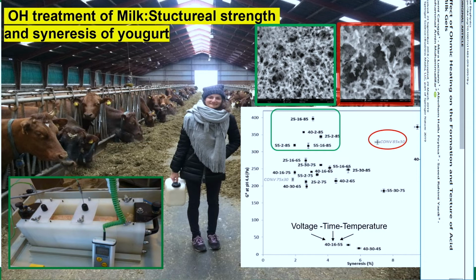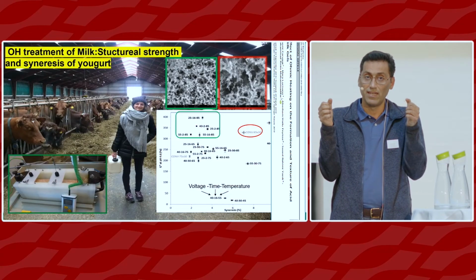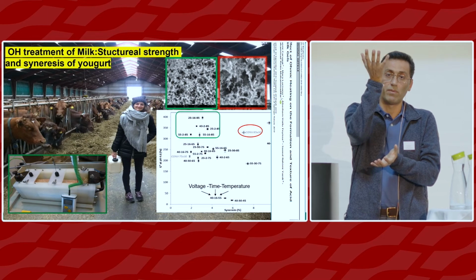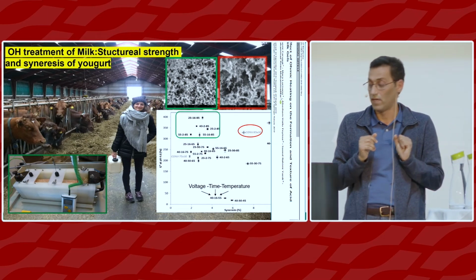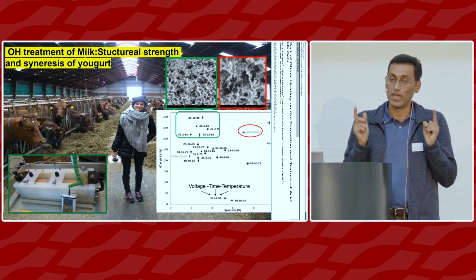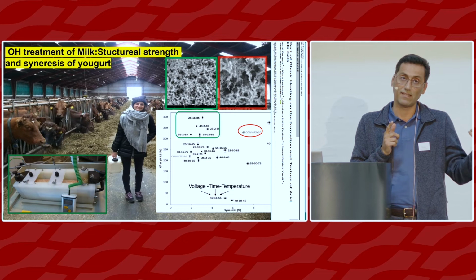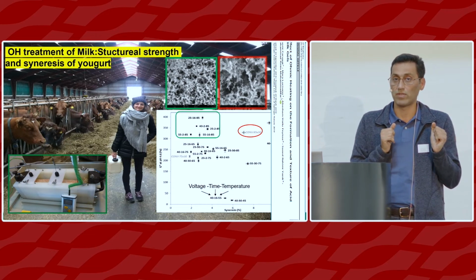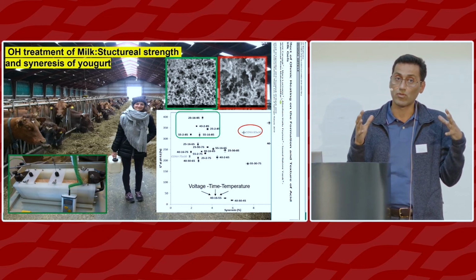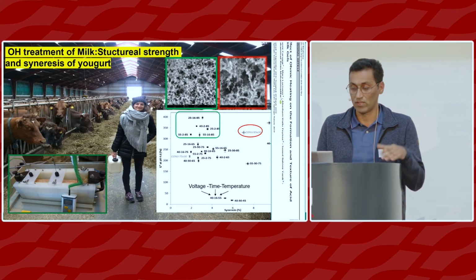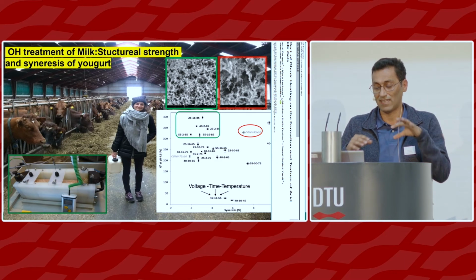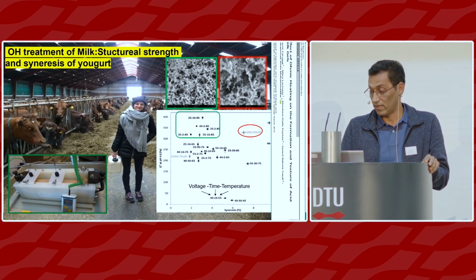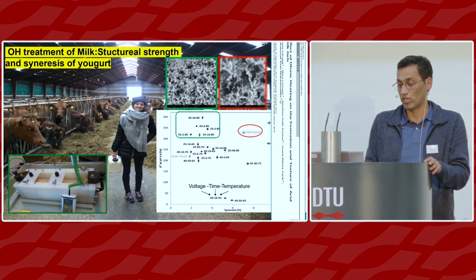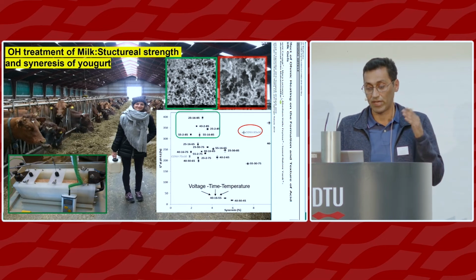But we did this without adding dry matter. But sometimes when you increase elasticity of these gels, the result is shrinkage, and then you have water repelling, which is called wheying off. But as you can see here, it seems that we have been able to adjust elastic and viscous components in the microstructure in a way that we have a stronger structure, but it's still not repelling water. So that means we have thickened that soluble part. So this is also proof that electric field is able to change mineral balance and functionality of proteins and aggregation pathways.